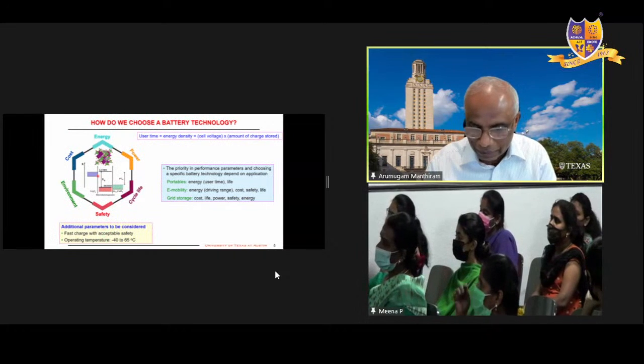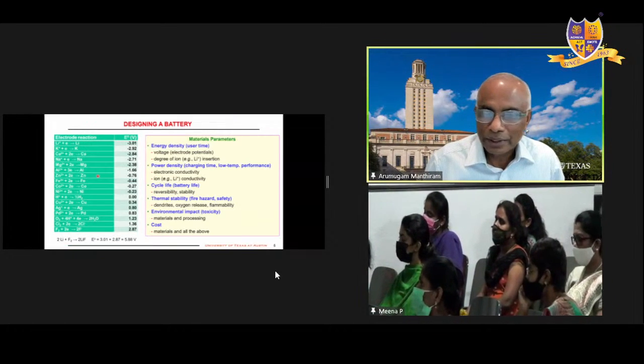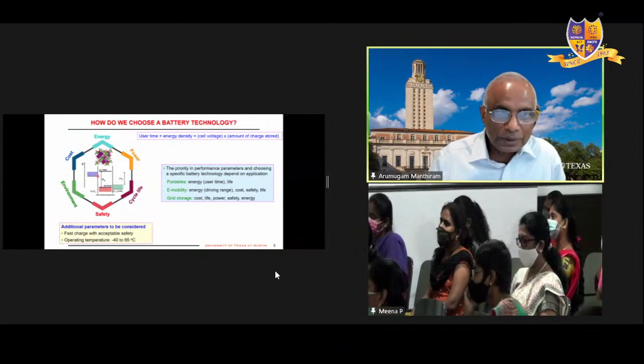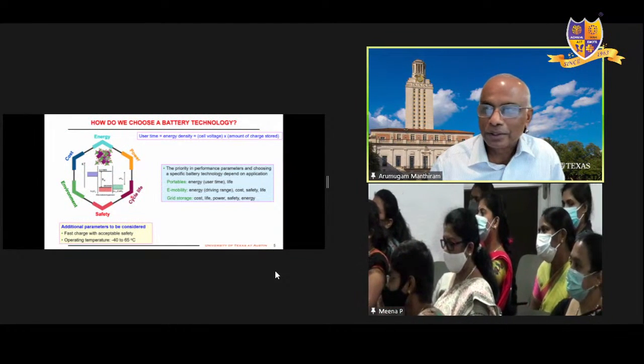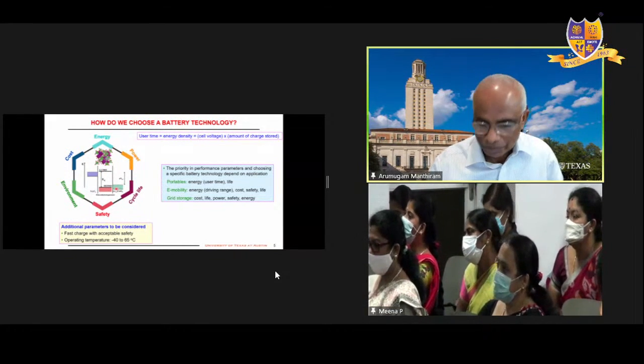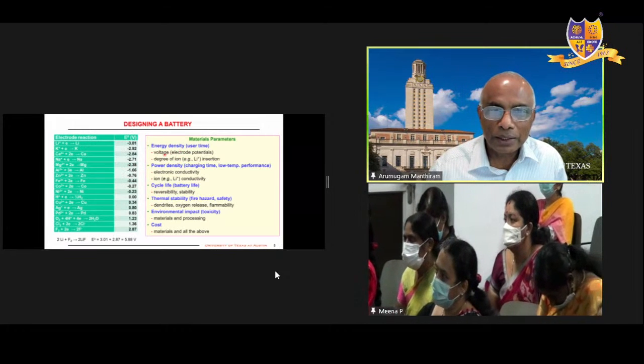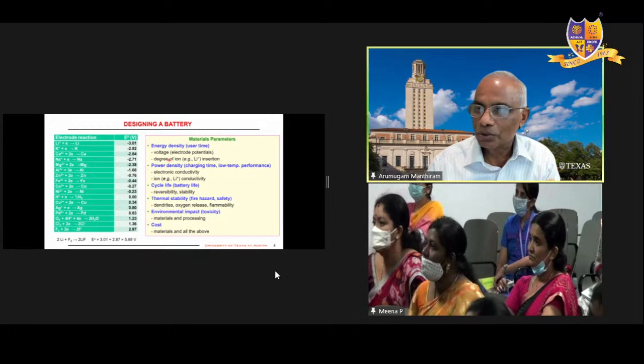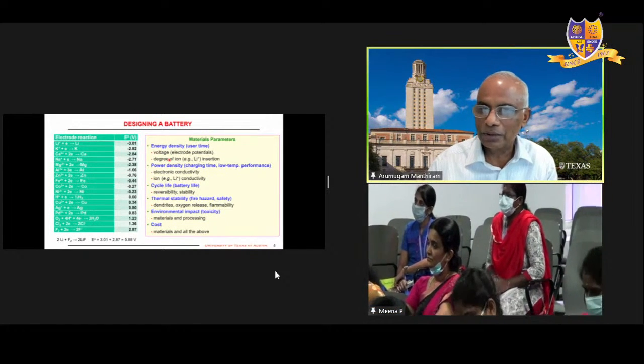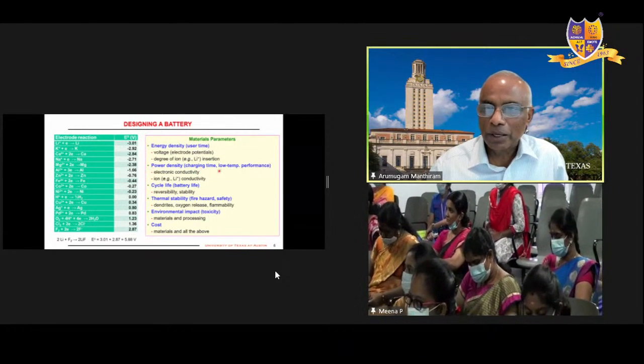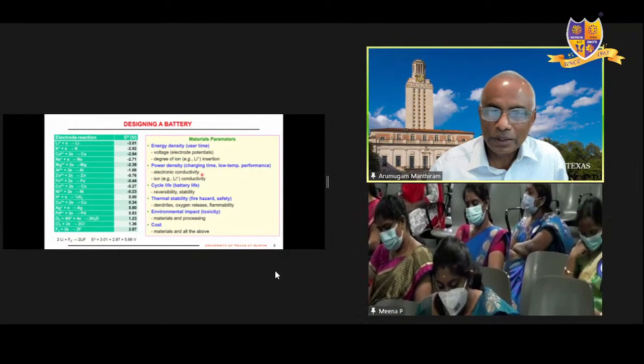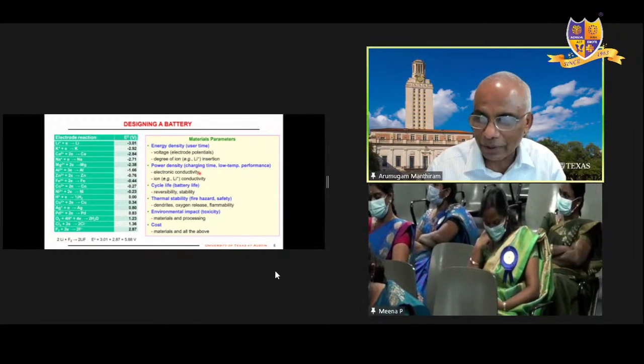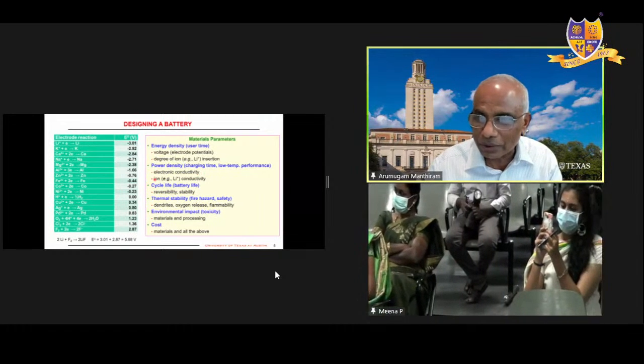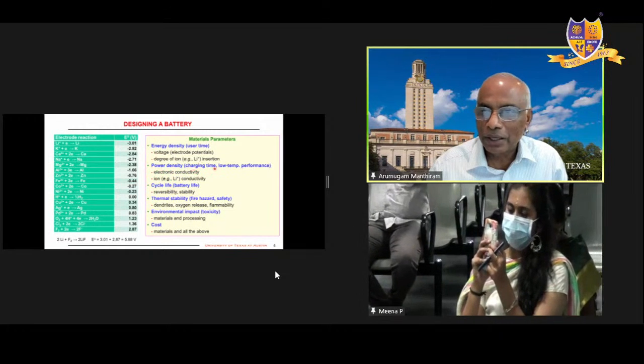So with that, how are all these parameters I'm talking about related to the physics and chemistry? I keep mentioning all these parameters are severely controlled by material challenges. So why do I say that? The energy density is a product of voltage and how many ions we can store in the material. That depends upon the structure. You have to use 3D transition metal ions rather than 4D or 5D transition metals because those are heavier. Power density, charging time, or low temperature performance depends upon the electronic conductivity of both the anode and the cathode, not the electrolyte. The electrolyte should be an insulator, and the ionic conductivity of the two electrodes and the electrolyte is what determines the power density and all these parameters.